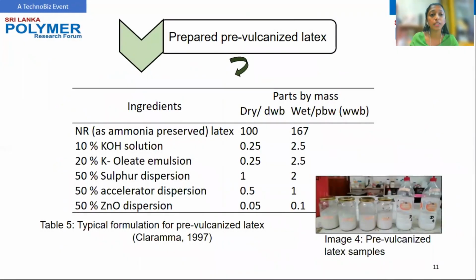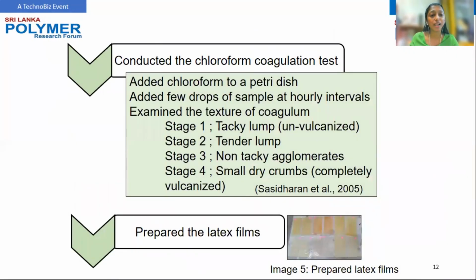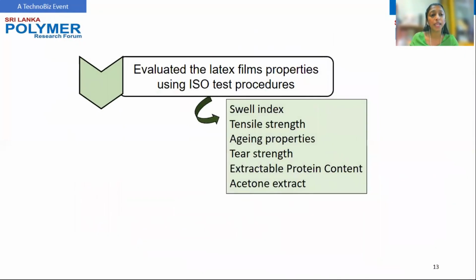According to the formulation in Table 5, pre-vulcanized latex using centrifuge latex and cream latex were prepared under three different types of accelerators separately. The extent of vulcanization was determined using the chloroform coagulation test while doing the pre-vulcanization. Then the films were prepared and the film properties were evaluated using ISO test procedures such as swell index, tensile strength, aging properties, tear strength, extractable protein content, and also the acetone extract.